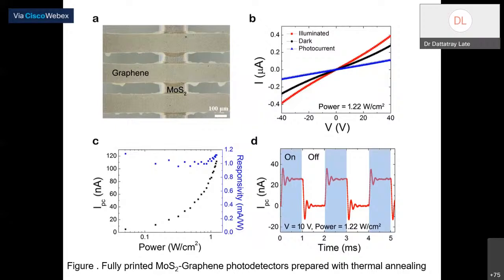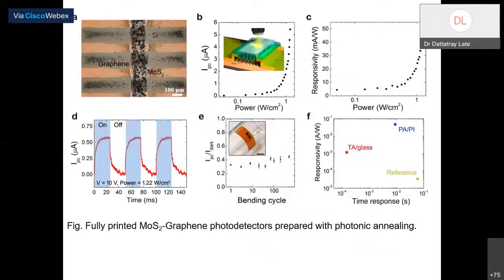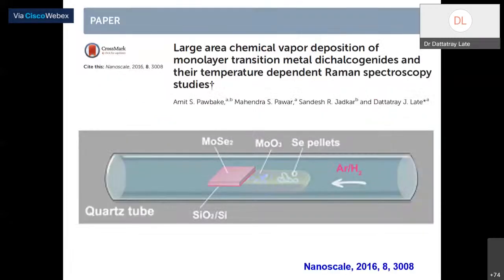So we have used this device as a photodetector. MoS2 graphene photodetectors are prepared with thermal annealing. So this becomes a very important parameter, right? A very important device, and it gives very good performance. Again, a fully printed MoS2 graphene photodetector, again annealed by the photonic method, and this gives a very good result as a photodetector.